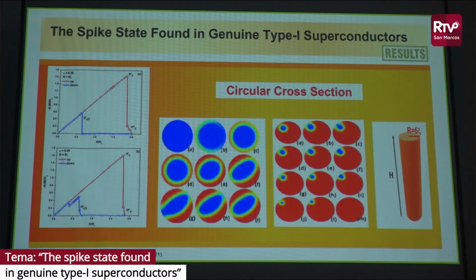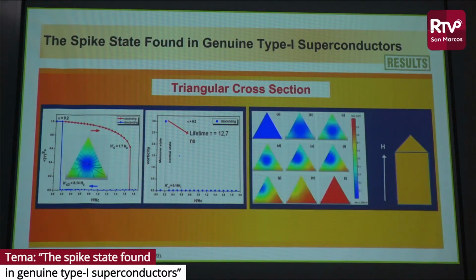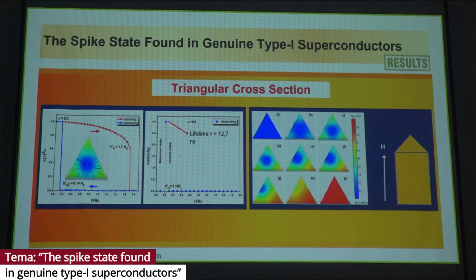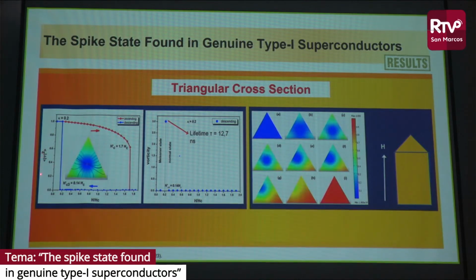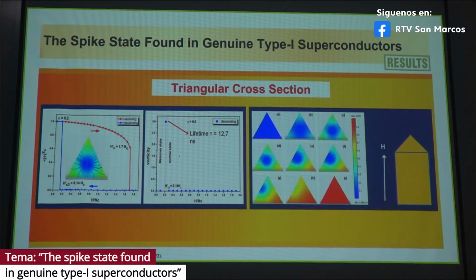So the same story appears also here, but this was calculated for a triangular cross section, and here I'm not using the magnetization curve, but it is similar. Here is the square of the order parameter, like you can find in Tinkham's textbook, Introduction to Superconductivity. But of course there is not this decreasing of the order parameter when you increase the applied magnetic field, because that is for bulk materials, and this decreasing here is because of the boundary effects.